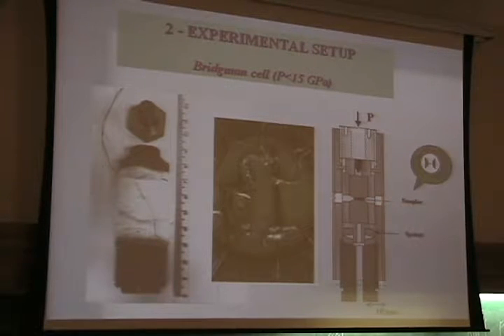Okay, we have a Bridgman cell that can go up to 15 GPa, and this is a typical installation for this pressure cell. You see here the sample, and you see here the lead. The lead is used as a pressure manometer for this kind of pressure cell. Okay, this is not an easy installation. Actually, Professor Eichler did this installation himself. And this is just an example. It's not the cerium platinum here. It's just one typical installation I decided to show you, but it's very nice, very beautiful.